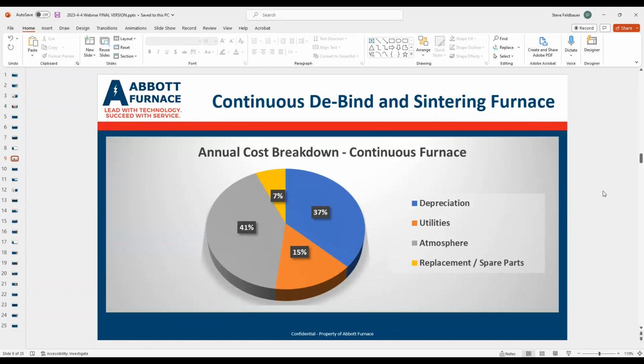And so if we look at the breakdown of the cost of this continuous furnace, you see that the vast majority of the cost is coming from the atmosphere, because this type of furnace would run 100% hydrogen, or potentially a hydrogen-nitrogen or hydrogen-argon mix, depending on the product that you're running and what you would like to do. The next thing is the cost. So you see depreciation and atmosphere are your biggest, and then third would be the actual utilities at 15%.